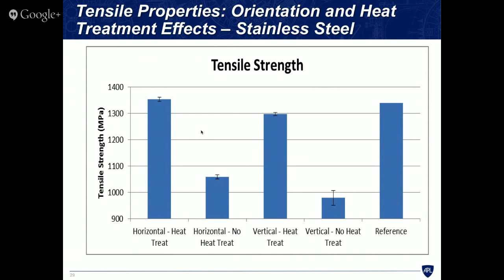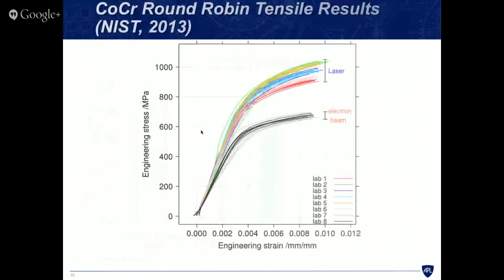So the horizontal bars with no heat treatment afterwards compared to the vertical bars, you can see the tensile strength differs by about 10%. But we reserved half of the samples and did a heat treat on those to try to improve the mechanical properties. And then you can see not only did the mechanical properties improve, but this difference actually became much smaller. And if you look at the horizontal heat treated specimens and compare them to a traditional casting or forging, you'll see that the properties are the same or even better. This is something that's repeated over and over again in the literature. It's not just us with stainless steel, but people have done this for other materials and seen similar trends. So the answer to the question is, if you do your orientation properly and you do your heat treatment properly, then you can get properties that are very similar to a casting or a forging.